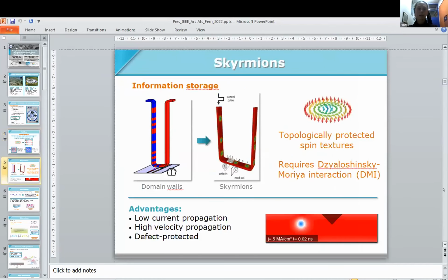So a quick overview of skyrmions. Of course, I will not show everything about skyrmions here, but to remember, at the beginning, more than 10 years ago, for information storage, there was the racetrack memory. That was the idea to have the information codified in domain walls that will have the motion by spin current. And along the years, we saw that there were some problems with the domain wall spinning, the velocity that the domain walls were able to achieve, and so on.